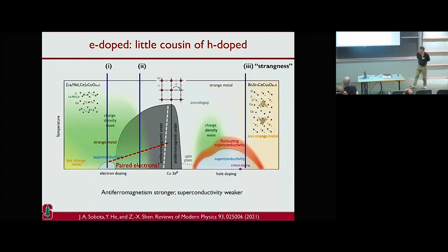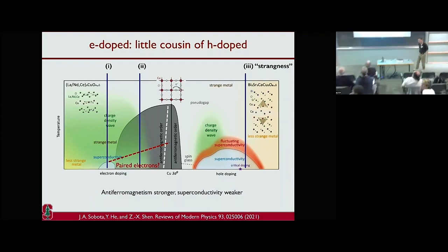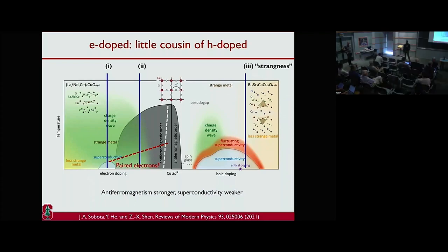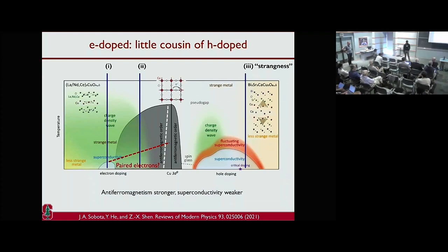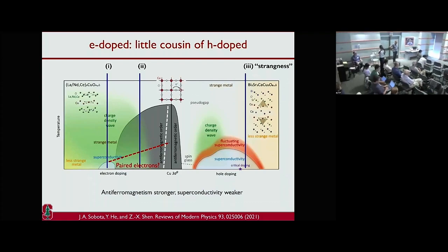Yes. If you have an arc, which is a series of poles, and it doesn't go to the Brillouin zone boundary, consider a path that goes through the arc and then back, avoiding the arc. There's no way to get the right sign of the real part of the Green function unless you have zeros. This is just an observation. The best argument for a Luttinger surface being physically relevant to the cuprates is the Fermi arc, as has been pointed out before.